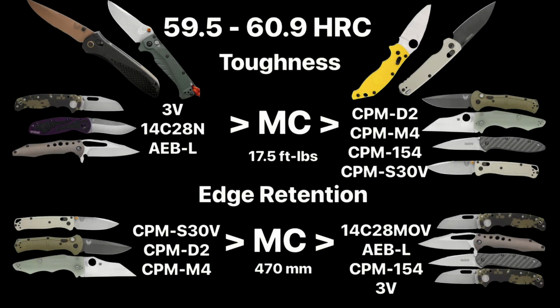Here are the results for the range between 59.5 and 60.9 HRC. MC in the center represents MagnaCut, and to the left of it there are the steels that, at least in the charts, perform better than MagnaCut in this hardness range. And on the right, for each category, there are blades that perform worse than MagnaCut in the same heat treat range. Next to the familiar steels, I placed pictorial representations of knives that use that steel in their blades. I did it for the purpose of sparking your interest in potential future videos.